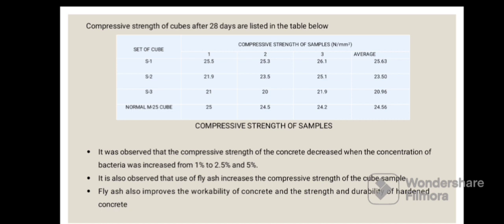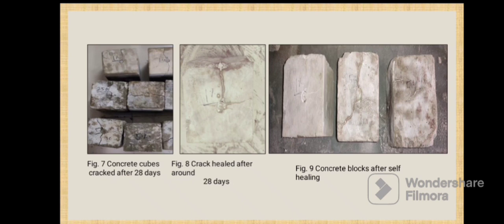Now, it was observed that the compressive strength of the concrete decreased when the concentration of bacteria was increased from 1% to 2.5% and 5%. It is also observed that use of fly ash increases the compressive strength of the cube sample. Fly ash also improves the workability of concrete and the strength and durability of concrete. This is the final result. Concrete cube cracks after 28 days. Crack healed after around 28 days. Concrete block after self-healing.